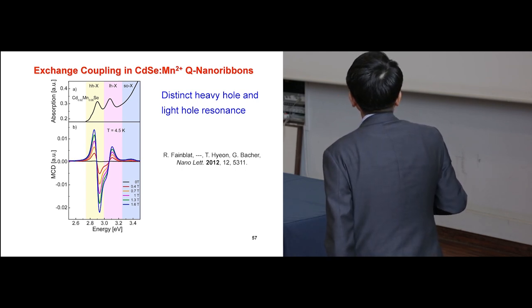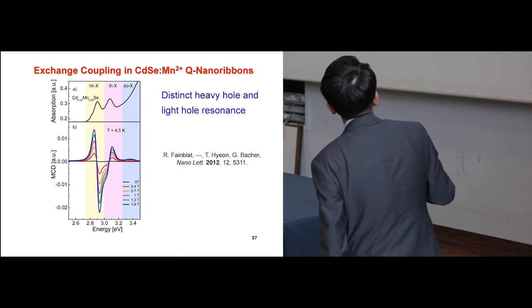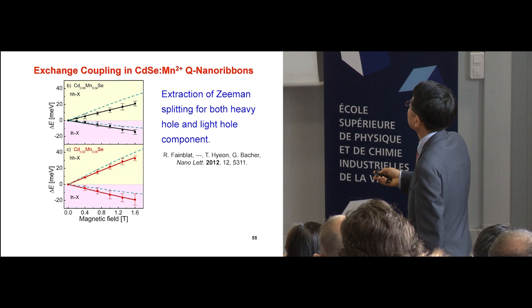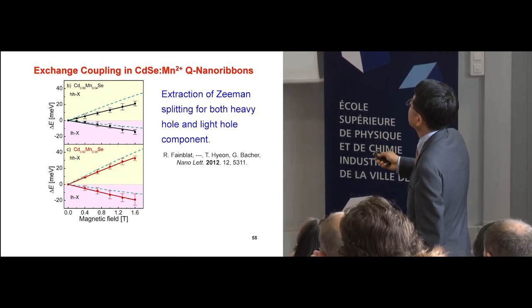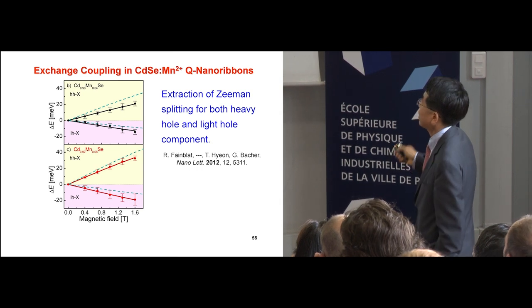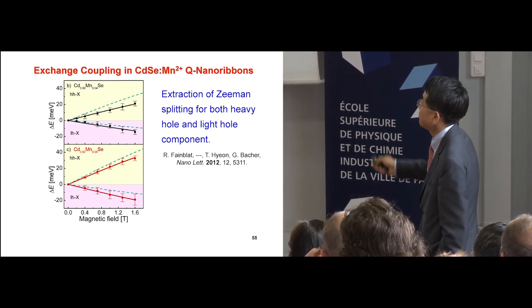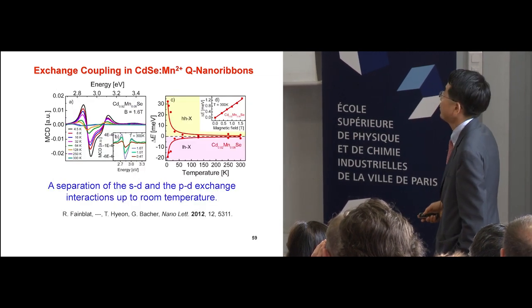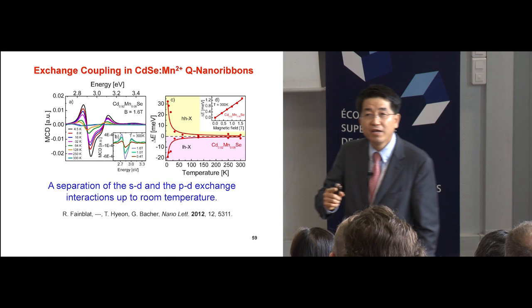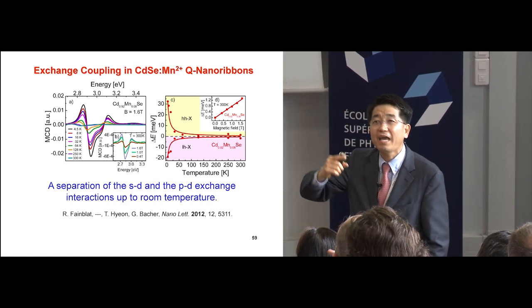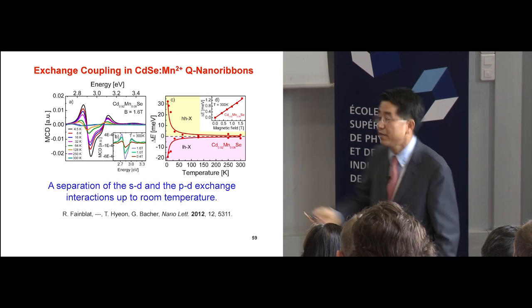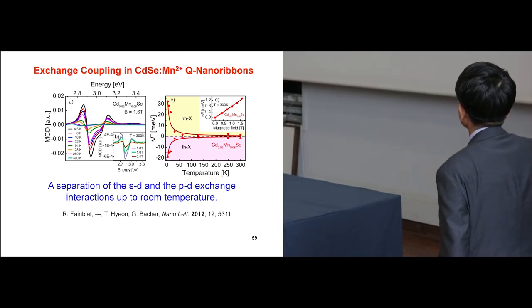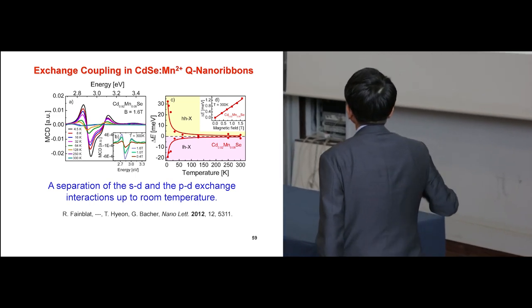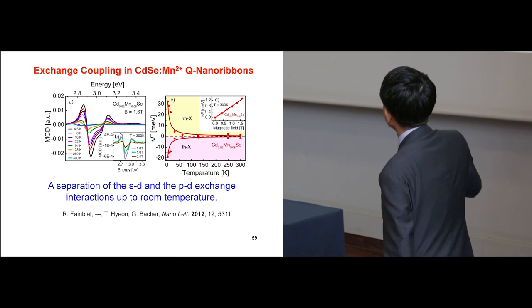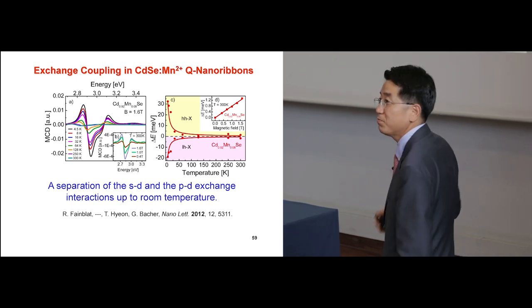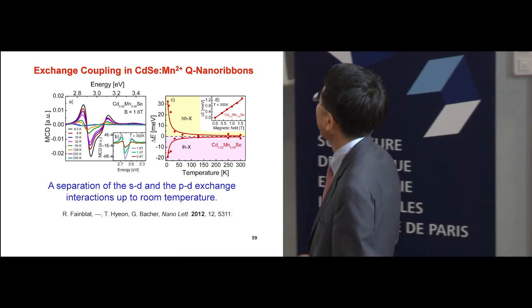On top of that, and actually up to room temperature, I think this is 4.5 Kelvin, we can extract information about not only the heavy hole, but also the light hole component, which can be clearly resolved here. Usually, what we put in Nature Materials is the sp-d coupling. But here, we can resolve the s-d and p-d exchange coupling constants separately, even at room temperature, not just at low temperature.